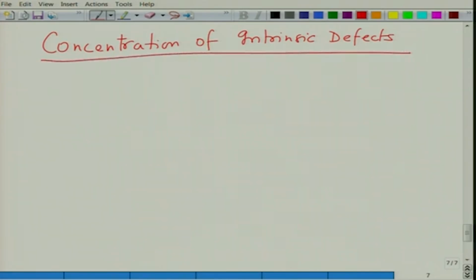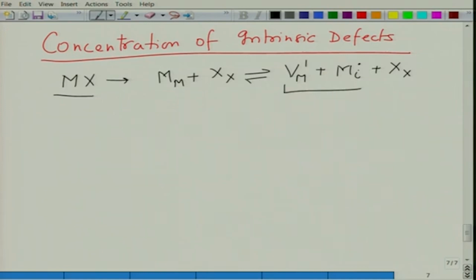So, let us say we consider a Frenkel defect. Consider a halide MX, and in that the reaction can be written as M_M plus X_X giving V_M plus M_i, and X remains at the X site. So, this is a Frenkel defect. You do not change the stoichiometry, the site balance remains the same: there is one metal site, one anion site, and the interstitial site is a site anyway. So, you do not create any extra sites in the system. What you are creating is a pair of metal interstitial and metal vacancy.